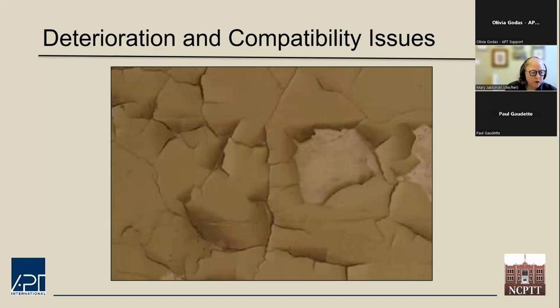Originally, this paint was to have been washed off and new calcimine paint applied, but over time there were layered buildups. So much of this calcimine paint is not particularly well bonded as it has aged. And one problem that is often discovered too late is repainting ceilings with latex paint. If there are water-based paints under the visible paint, failure often occurs because moisture penetrates cracked paint and it dissolves the glue in the distemper paints. Large sheets of paint can fall, and it's not uncommon for there to be a complete failure of all coats.